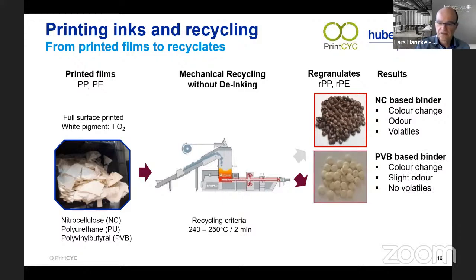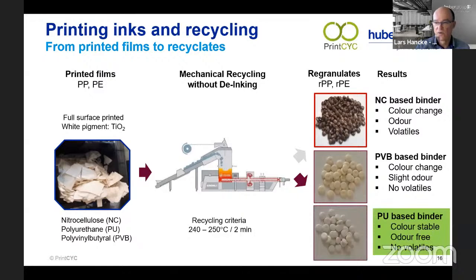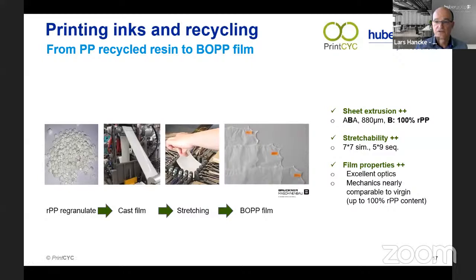With the PVB inks, PVB white was already much, much better. So we only have a slight change of the color. You can see here, it is getting a little bit more yellowish than the starting material, but no odor and no volatiles. And the best performance we achieved with the polyurethane-based inks: we have no volatiles, no odor, and we have a clean white shade. So no change in terms of the color coming from any kind of side reactions of the binder. And based on these positive results for the polyurethane-based inks, we made some further investigations. So what can we do with this type of regranulate?